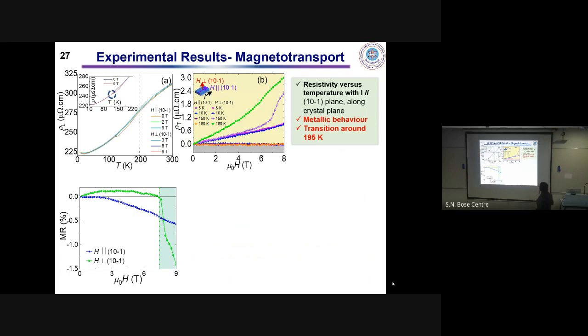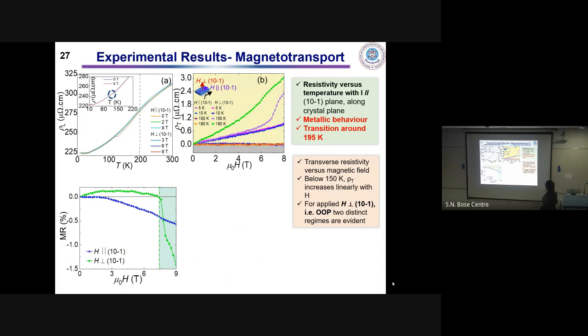Now, this shows the temperature dependence of the resistivity. The geometry is this: the current is always in the plane of the sample, and what we have observed is that throughout this temperature range, we could see a metallic behavior and a change in the slope at around 195 Kelvin, which matches with the magnetization data.